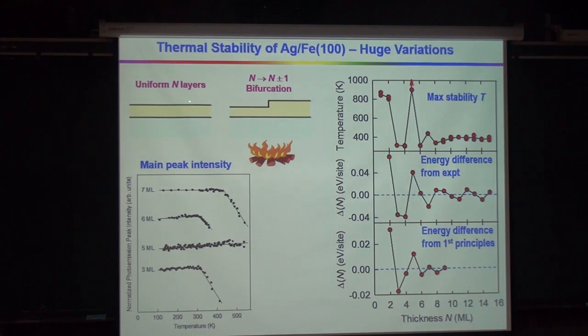So we make a uniform film, we raise the temperature, and then at some point the film will bifurcate into n plus 1 and n minus 1. Atoms are conserved, of course, we have the right number of atoms. But the film then becomes rough, and then you heat up more, and it becomes rougher. That we can actually check very carefully, but very easily.